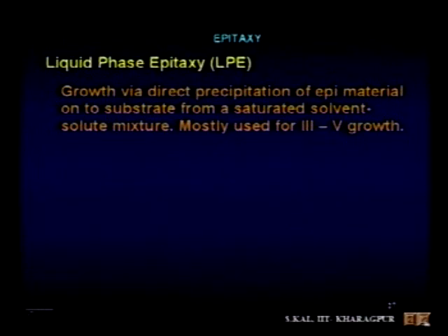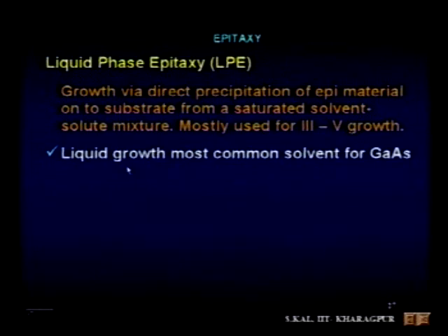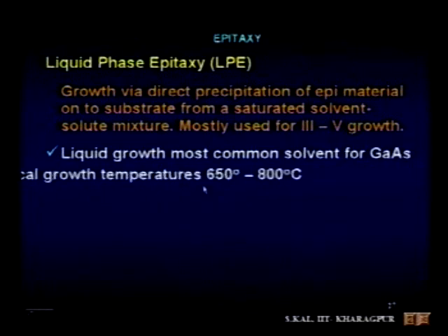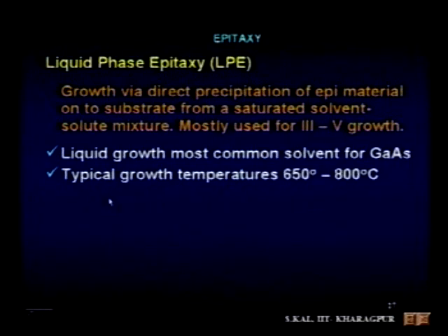LPE, you know, is growth via direct precipitation of epitaxial material onto the substrate from a saturated solvent solute mixture. Here the precursors are not gas phase, they are liquid phase. So you have to have a saturated solvent solute mixture. It is mostly used for 3-5 growth. Typical growth temperatures are 650 to 800 degrees centigrade in this particular case.